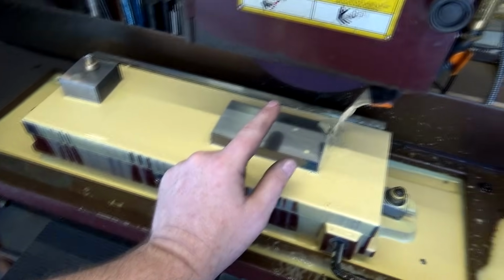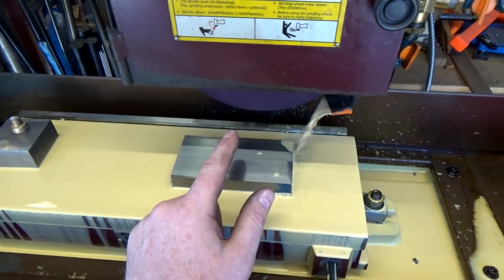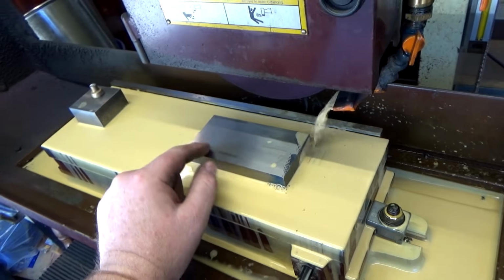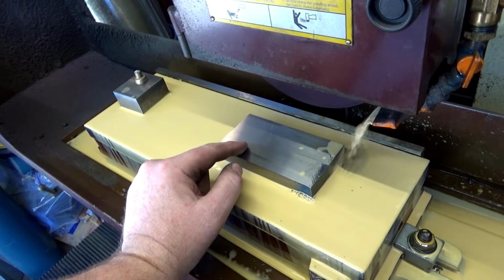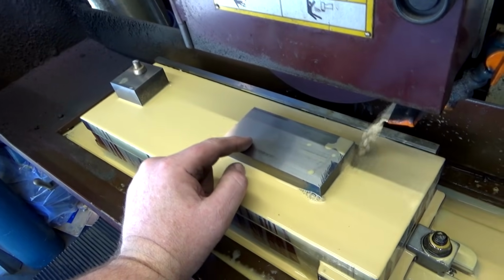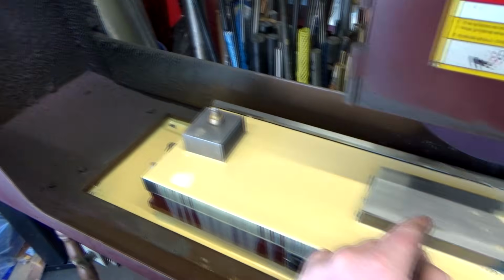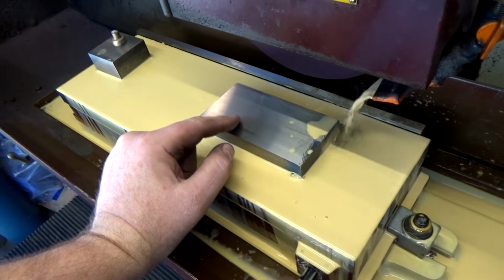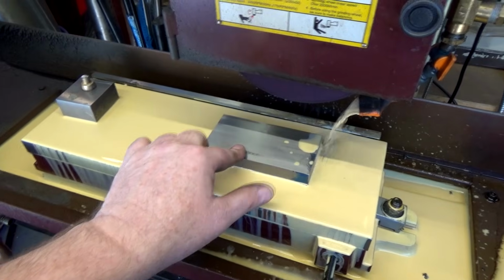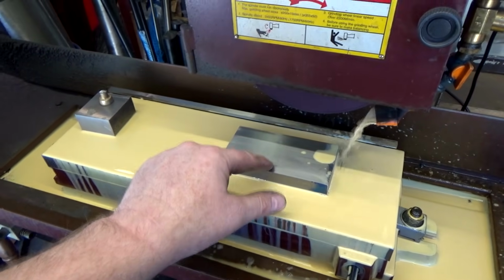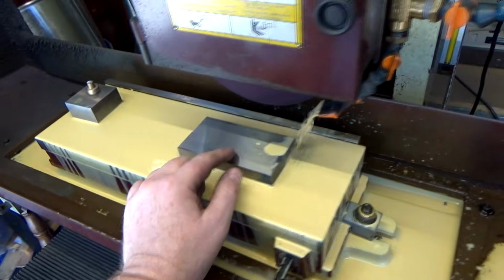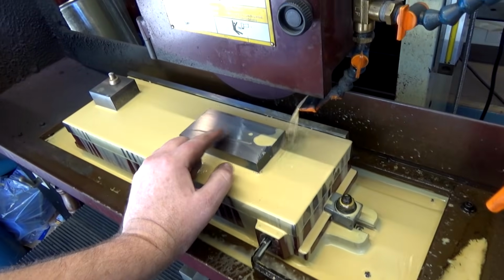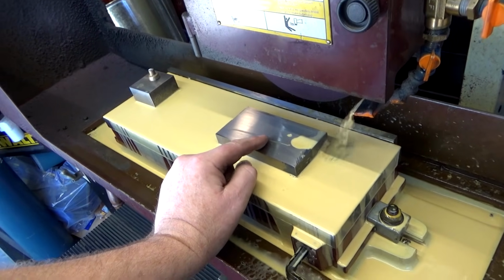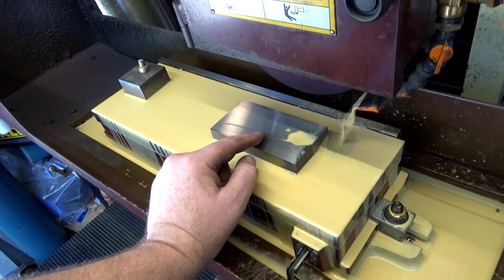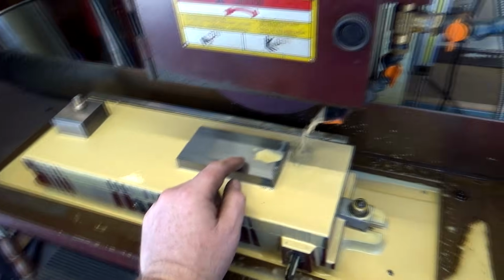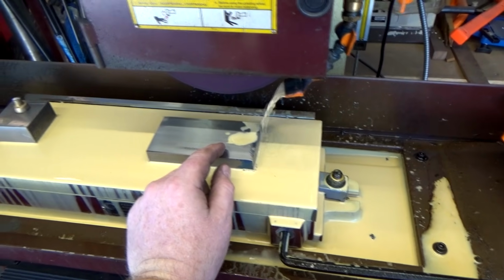And because this stuff is pre-hard, it just wears my wheel out really quickly. So I was taking like thousandths depth of cut each time, and I'd have to redress it after like every 5 or 6 thousandths kind of thing. That's why I left the diamond on the magnet. What you can tell when it needs dressing, it starts burning like crazy. And you can't feel those, but there's some burns on the top here. Yeah, it burns across the whole thing and then cuts weird on the backstroke. So I learned really quickly that you got to redress the wheel constantly, which is just really crazy. This stuff's tough. I guess it's abrasion resistance, and we're seeing the abrasion resistance.